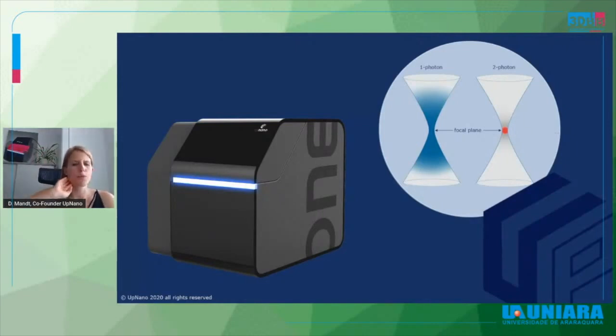So therefore, you can work within the material volume. There is no repetitive material appliance necessary. Different to the stereolithography process you might know, which you can see on the left side. So when you apply the light, the material is hardened along the whole beam. So this is the difference. And therefore, with the 2PP process, you can achieve a higher spatial resolution and you can work within the material volume.